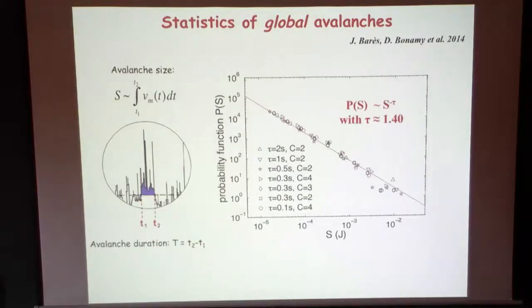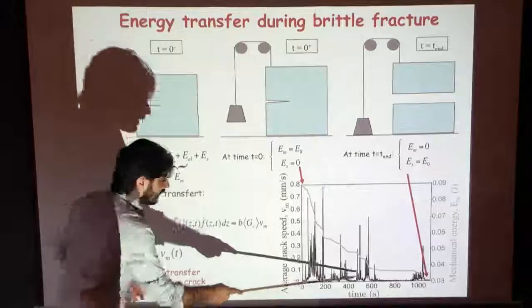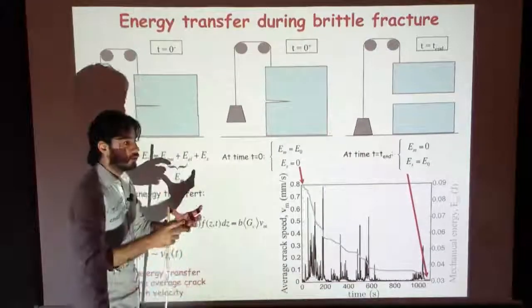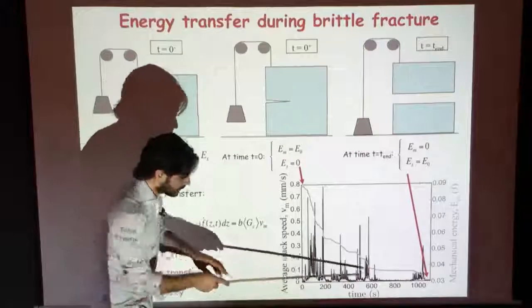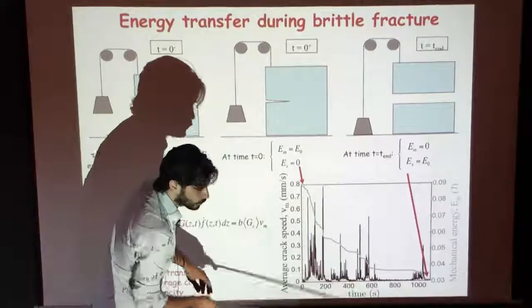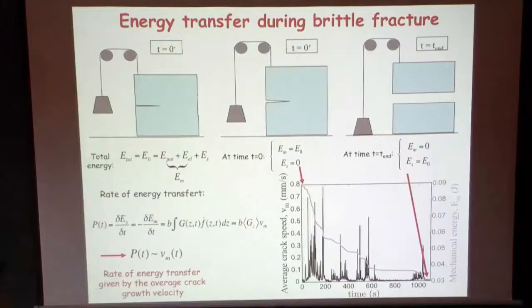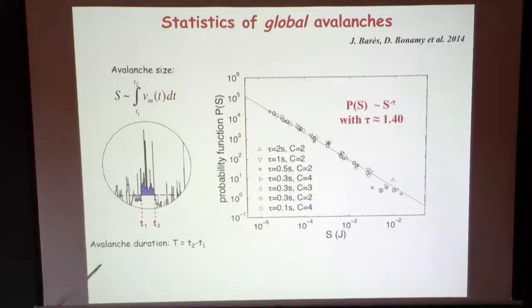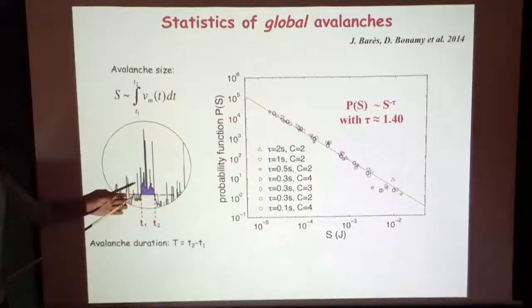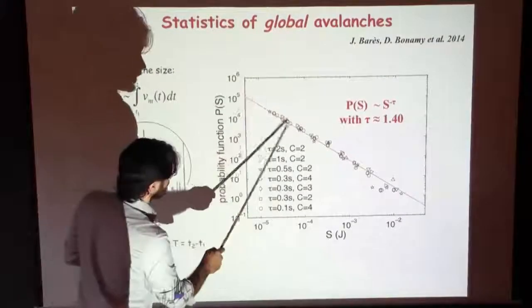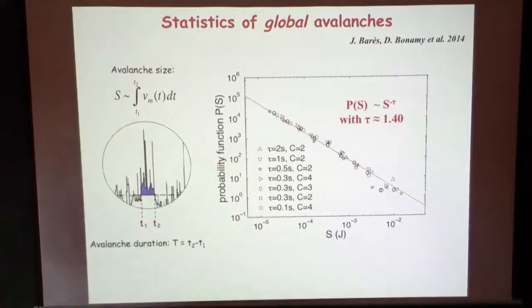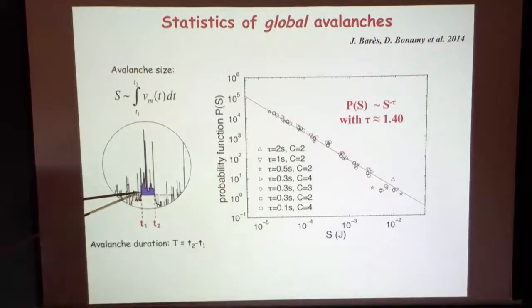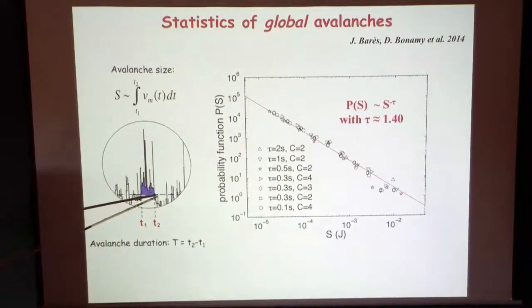So now, if you want to define an avalanche, or the burst of energy you transfer from mechanical to surface, you need to integrate your velocity signal from the beginning of the avalanche to the end of the avalanche. That's what we do here. That's what classically you do, and that's what Jonathan Barés and Daniel Bonamy have done in artificial rock. They have worked on a designed heterogeneous material to measure these avalanches, and they have recorded the velocity signal as the one shown before, and defined avalanches using a threshold.